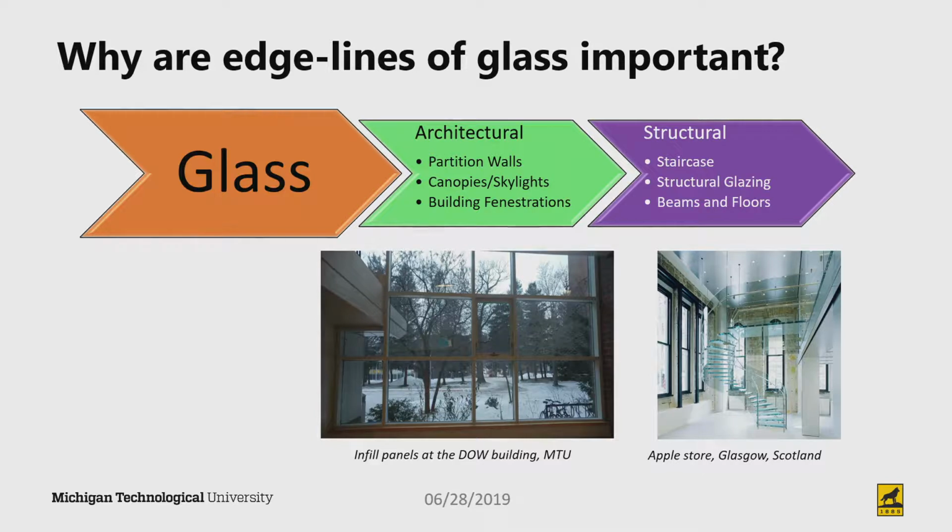So right now, ASTM E1300 is based solely on infill panels, and it just addresses the strength of the surface of the glass. And there are several spots throughout the standard where, when we start putting the edges in significant stress, the standard just doesn't address those issues. When you have partially supported or unsupported edges, the standard starts hand-waving a little bit. What I'm trying to do is get to where we can quantify the strength of the edges in a meaningful way, in line with the philosophy of the glass failure prediction model the standard uses.